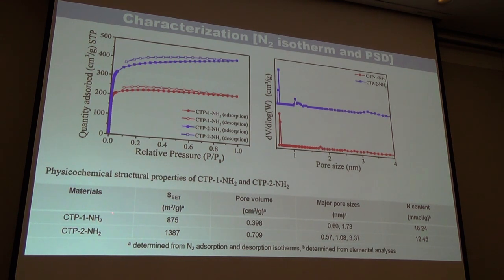And these two materials show surface areas of about 875 and 1387 square meters per gram. Meanwhile, the CTP1 material shows a nitrogen content of 16.24, whereas CTP2 has a nitrogen content of 12.45 millimole per gram.